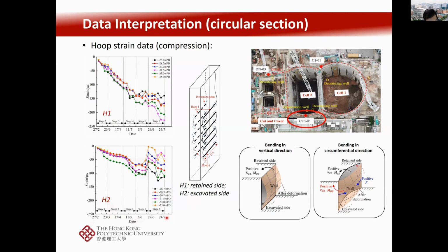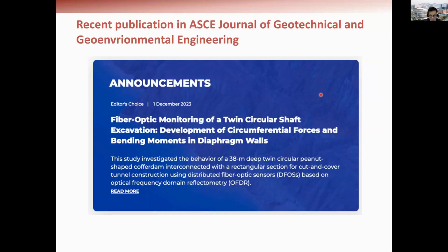at different construction stages. So if we take a moment to think about why this happens, it's basically because just now we said that if you have bending of the wall in the vertical direction, you have different strains in the front side and the back side. And if you have bending in the horizontal direction of the wall, you will also have a difference in the compressive strains comparing the front side and the back side. So by doing these measurements, we're actually able to capture the bending of the wall along the circumferential direction when you have a circular cofferdam utilizing the hoop action to support the excavation. So this is quite interesting behavior that we capture.